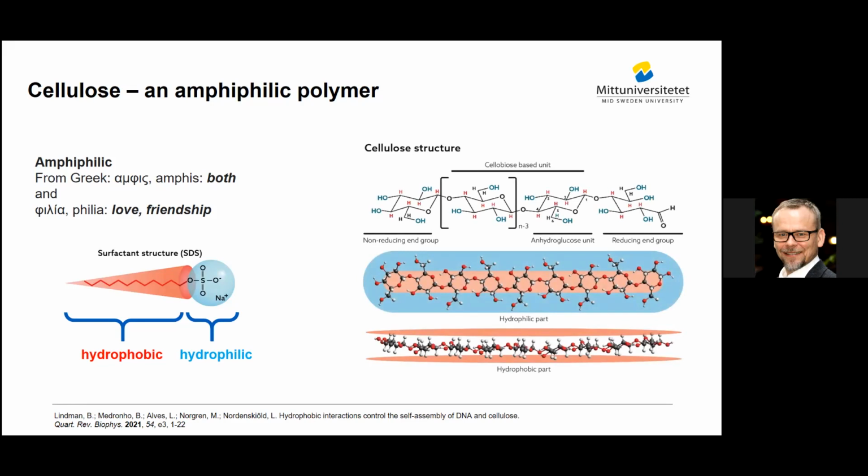If you look at the polymer chain, you can see you have OH groups that are sticking out, pointing in one direction, and you have also the CH groups from the backbone of the cellulose that are directed in another direction. So you have both these equatorial and axial properties. If cellulose lies down, it has one property at the edges, and another in the plane.